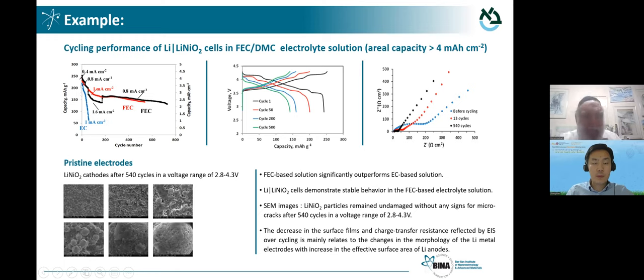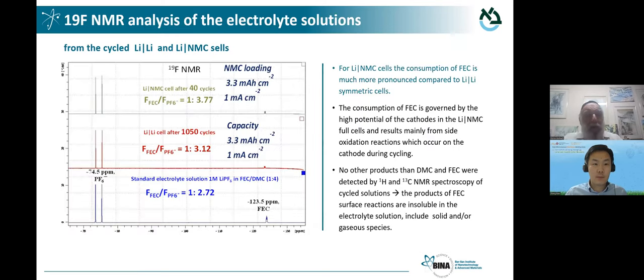And compared to the reference EC-based electrolyte solution, we see with LNO, there is a capacity decay. The cells are not optimized, they're coin cells, but we could demonstrate hundreds of cycles. And after prolonged cycling, no change in the negative or positive electrode, no cracks, nothing. The positive electrode remains fully completed and unaffected. The problem is the lithium side, and the problem comes through crosstalk.